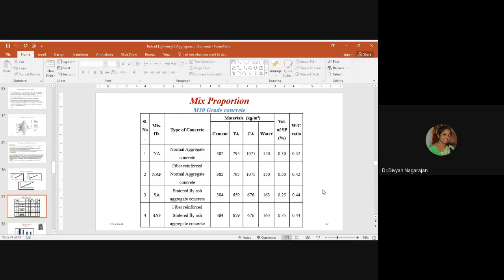This is the quantity of materials I have arrived at through MATLAB programming. The types of concrete used in the investigation were normal aggregate concrete and lightweight aggregate concrete, that is, sintered fly ash lightweight aggregate concrete with and without basalt fiber. The normal aggregate concrete is designated as NA. The fiber reinforced normal aggregate concrete is designated as NAF. The sintered fly ash aggregate concrete is designated as SA. Fiber reinforced sintered fly ash aggregate concrete is designated as SAF.